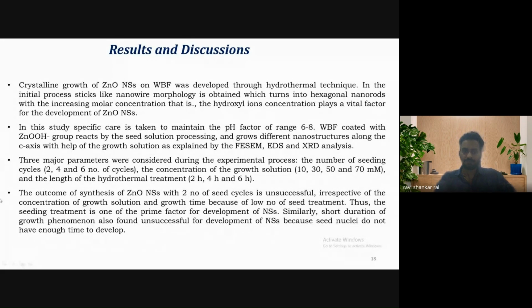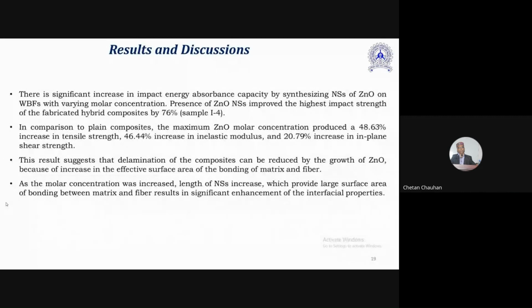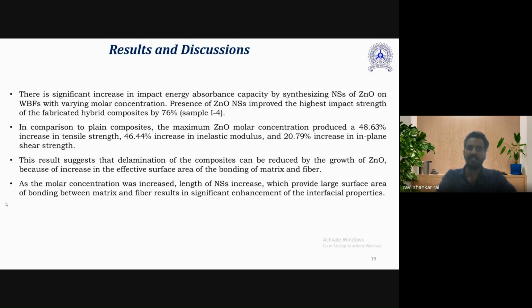And after all, Dr. Ravi, just conclude it. Yes, sir. There is a significant increase in the impact energy, and we have achieved the highest impact energy increase of 76% for the sample I4, which is the 70 millimolar concentration sample. We have also achieved a 48.63% increase in tensile strength, 46.44% increase in elastic modulus, and 20% increase in in-plane shear strength. This result suggests that the delamination of composite can be reduced by growth of ZnO because of the increase in the effective surface area of bonding between the matrix and the fiber.